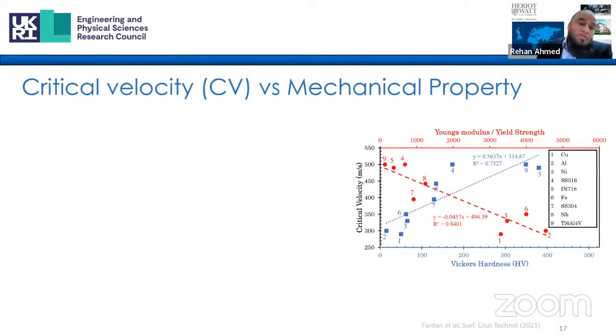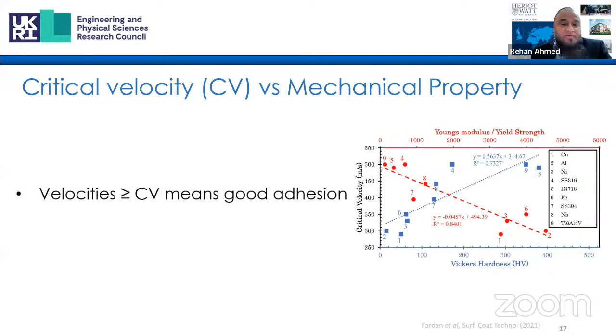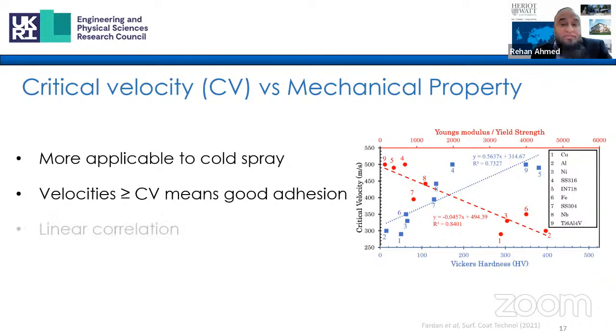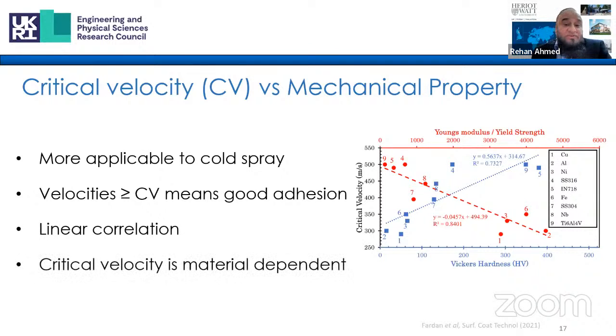So if you are able to model the splat behavior and residual stress behavior, in certain instances, we can extract some additional information. For example, in cold spray, these models can help understand the influence of critical velocity on particle adhesion. Too low velocity can lead to particle rebound, and too high velocity can cause excessive jetting, leading to material loss. So in terms of the bonding mechanisms, there are two schools of thought which rely on either the adiabatic shear instability or the pressure waves causing the hydrodynamic plasticity when we're looking at the bonding mechanisms in cold spray coatings.